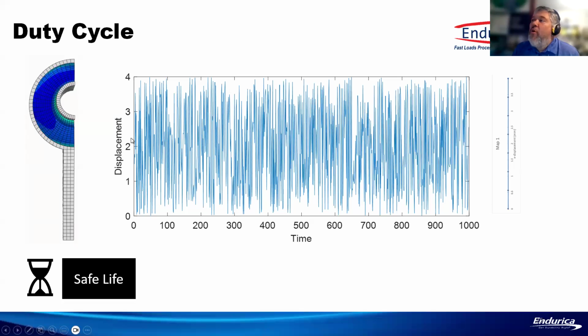Now, of course, it would be very expensive to run a finite element job through this 1,000 seconds of history. But if you look at this, this is just a displacement in a single direction. You might say, well, why don't we just model the displacement of the part from 0 to 4 millimeters? And since this is nonlinear, maybe we take 8 steps to do that. And then when I want to know what's the strain at any of these times, I can take these results from the 8 steps that I computed, and I can just interpolate between the steps, right? So it's treated as piecewise linear and we just interpolate.